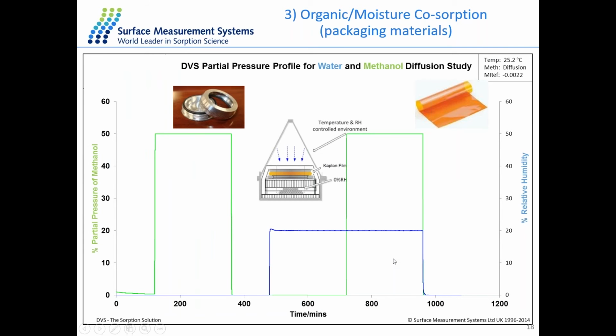So here we have the case study with the Kapton film sample, and we perform the sorption of both water and methanol, as well as the co-sorption of two different vapors. And this methanol molecule just represents any organic vapor or even a kind of flavor molecules escaping from the packaging material. So we set up the experiment mainly for three different stages.